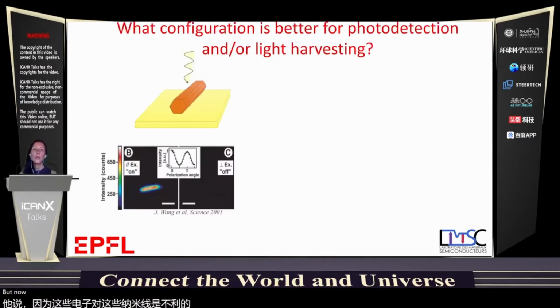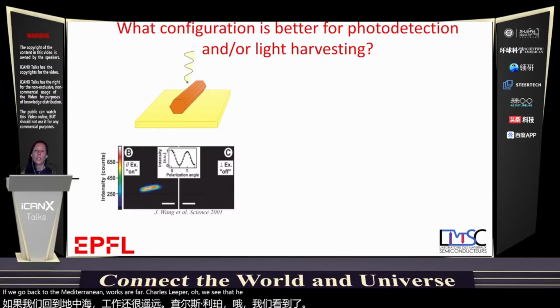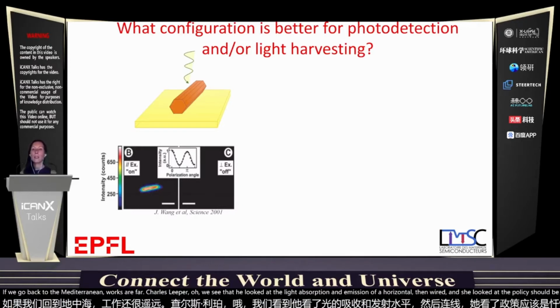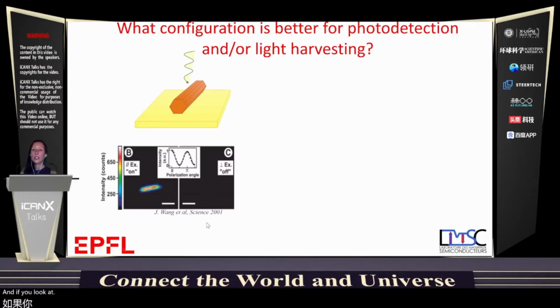But now, if we look at the photodetection scheme or light harvesting, what is better: to have nanowires lying on a substrate, or would you like to have them vertically? If we go back to the very pioneering works of Charles Lieber, we see that he looked at the light absorption and emission of a horizontal nanowire, and he looked at the polarization dependence. And if you look at these images here, what you see is the emission of light.